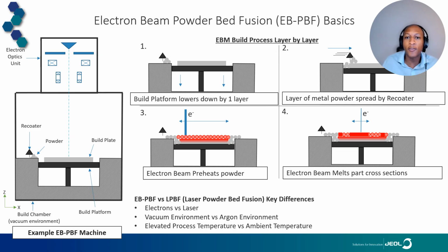So some specific differences between electron beam powder bed fusion versus what's more commonly understood, laser powder bed fusion, is that we use electrons as our energy source versus a laser. We have our process in a vacuum environment, whereas with a laser you typically use an argon purge across the build platform. And lastly, one of the major differences is that we keep an elevated powder bed temperature throughout our process, versus in most laser-based technologies, it's at ambient temperature. And there are some very unique benefits that we have by maintaining an elevated process temperature.